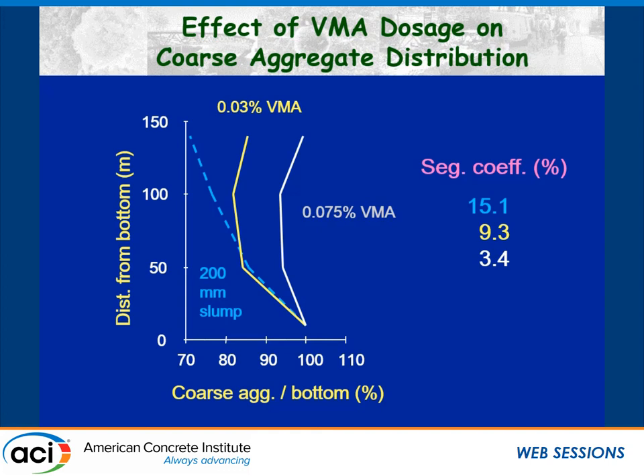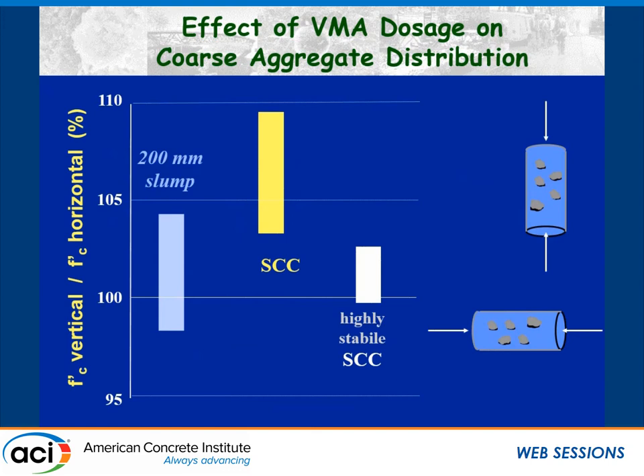Now, what does that mean in terms of in-situ properties? So one good way of looking at whether you have a stable concrete or not, go to that wall element at a certain height, take a horizontal core, and take a vertical core, and test them in compression or tension or elastic modulus, and see if those values are more or less similar. So that's what's happening here. The 200 millimeter vibrated concrete, if you take a vertical core compressive strength, divided by the compressive strength of the horizontal core, and these are many cores over the height, you see that there's a very large variability. Typically, the vertical one would be higher.